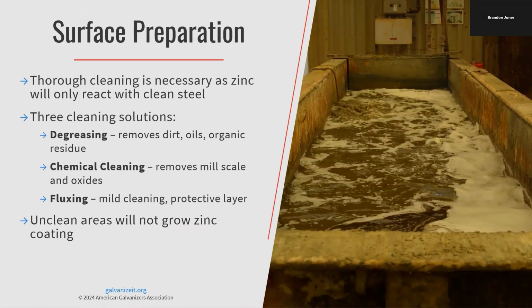Surface preparation is absolutely necessary, as zinc will only react with clean steel. When the steel gets dipped in the hot zinc, it actually has a metallurgical bond and fuses together, so it needs to be clean in order for that to happen. It goes through three cleaning solutions: degreaser, for dirt, oils, and organic residue; and chemical cleaning, for mill scale and oxide, so rust.